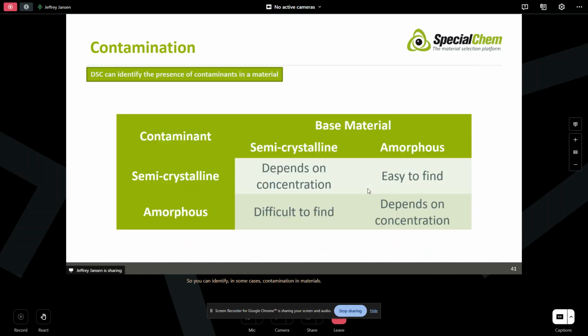So let's look at this little matrix here about what you can do. If our base material is semicrystalline and our contamination is semicrystalline also, well, it depends upon the concentration. If you've got a contaminant at 1 or 2% in your base material, you may not see it. If our base material is semicrystalline and our contaminant is amorphous, well, that amorphous peak is very, very weak. It really is almost impossible to find. But if we have an amorphous material and we have a semicrystalline contaminant, which is the case we showed here, well, that's pretty easy to find.